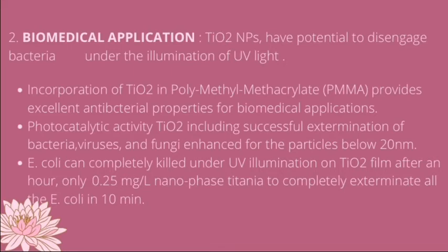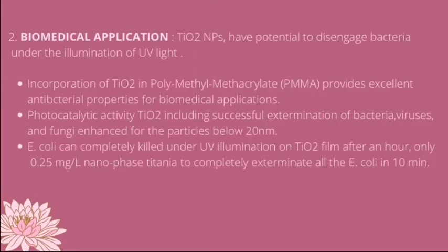The photocatalytic activity of titanium dioxide, including successful extermination of bacteria, virus, and fungi, is enhanced for particles below 20 nanometers. E. coli can be completely killed under UV illumination on titanium dioxide film after an hour, but with 0.25 milligram per liter nanophase titania, all the E. coli are completely exterminated in 10 minutes.